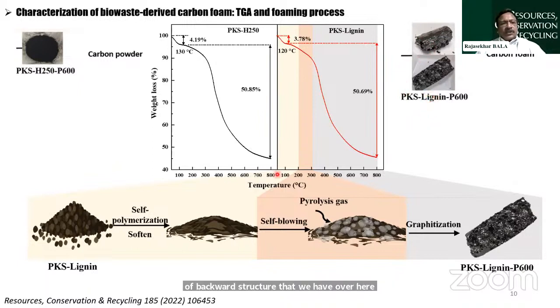So how do we produce that? You can imagine that once you get lignin out of the hydrothermal reactor, when you do the pyrolysis, you have a series of processes happening in a sequential manner that will eventually lead to the carbon foam. This is what we call self-foaming. It's a self-polymerization or aromatization process happening over here. Initially you have this polymerization, and then later on you volatilize certain gases from the product, and you could see the kind of pores we have here.